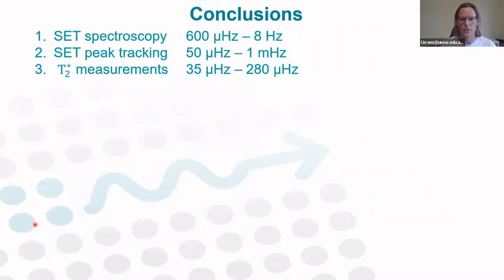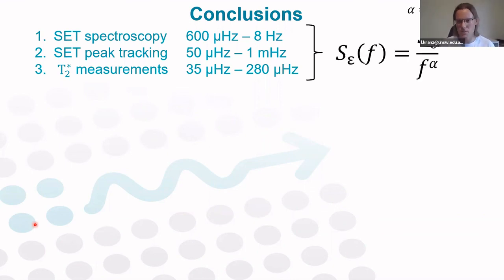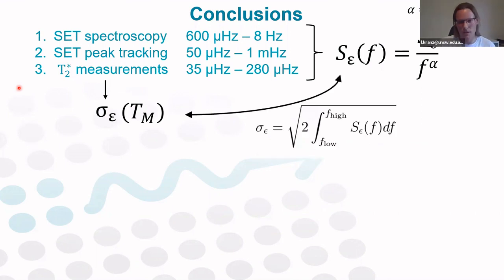So we showed three different methods of measuring charge noise: SET spectroscopy, SET peak tracking, and dephasing measurements on the qubits. And we applied them to different frequency ranges. Based on these measurements, we extracted the overall noise spectrum in our device, which follows a 1/f frequency dependence over at least 4 frequency decades. Moreover, from T2 star measurements, we were able to calculate the standard deviation of detuning fluctuations sigma epsilon, and we showed that this depends on the total measurement time. And we also showed that these two metrics are correlated.